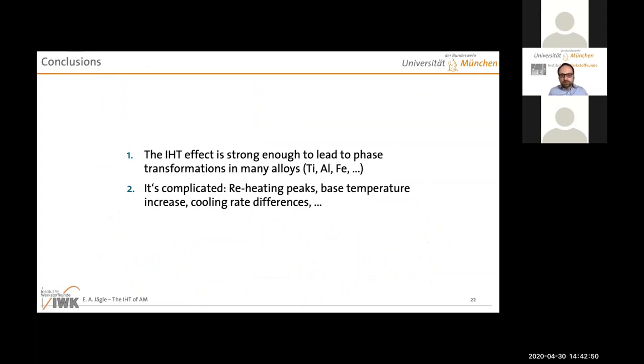So let me summarize here with this happy story and give you two very simple take-home messages. The first take-home message is that during almost all of the additive manufacturing processes, we have some kind of heat input. We call that intrinsic heat treatment. And that effect can be strong enough in some materials to lead to phase transformations. Probably not if you have a very simple austenitic stainless steel, it will probably not care about the intrinsic heat treatment. If you have a solid solution strengthened aluminium alloy, it will not care about these subtle effects. But the materials that we have looked at here, where you have martensitic phase transformations, where you have precipitation phase transformations, yes, this is significant.